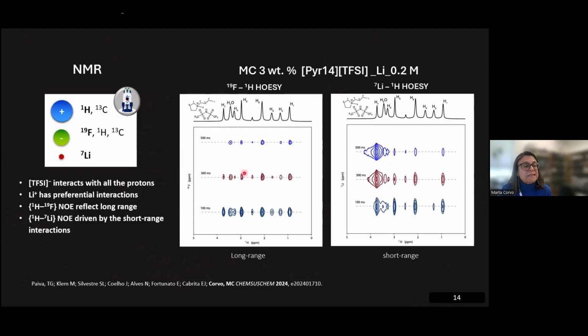And because the Larmor frequencies of fluorine and proton are quite close, this is giving you something that is called long-range behavior. What does this mean? This means that we are looking at the polar and non-polar domain patterning among our gel polymer electrolytes. The polar domains are the ones that you can relate here with the charged part of the molecule, and the non-polar ones are the ones that are far apart in these side chains. And of course, here we are looking just at these alternations between polar and non-polar domains. And you see that the cation and the bis(trifluoromethanesulfonyl)imide anion are quite close to one another.